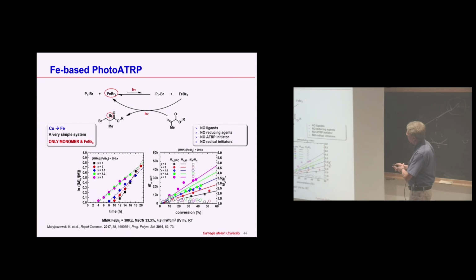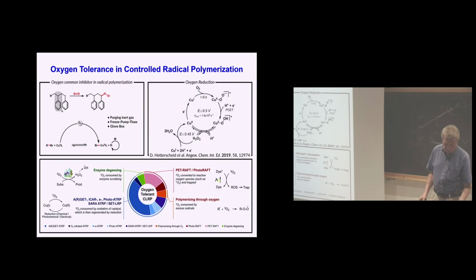And if you have more iron tribromide, which will be progressively reduced to these activators, iron 2 species, in that case, you will see an induction period, because you need to reduce approximately 85% of iron 3 to iron 2 to start the reaction. Meanwhile, it produces initiator, and a longer induction period produces more initiator, shorter chains, lower molecular weight. So it's really the simplest way you could think of: light, monomer, and iron tribromide, three inexpensive species, and you can make block copolymers this way.